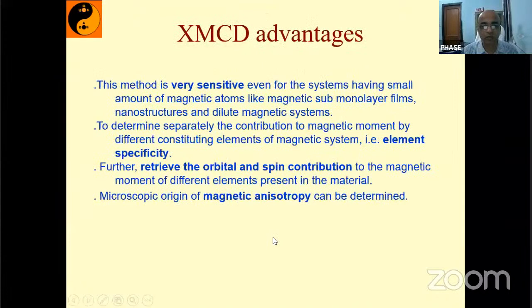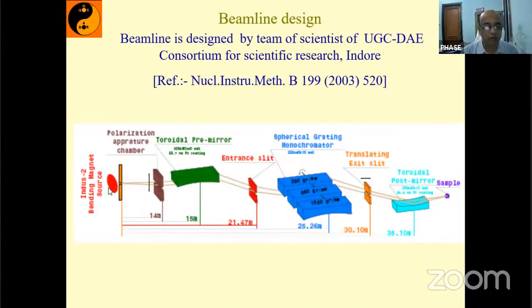So how can one do that? Basically the same beam line that we have. We have the source, then we have the aperture. The only thing is that now for the aperture, we have to tap the beam above or below, not exactly at the center. So instead of focusing the direct beam from the center on the pre-mirror, we are moving the aperture. For left circular polarized we move the aperture above, and for right circular we go below. Other components are the same: grating, post mirror, pre mirror, slits. But we are putting one additional aperture here. That aperture will select the position of the beam, and that will decide how much polarized light is coming inside the synchrotron beam line.